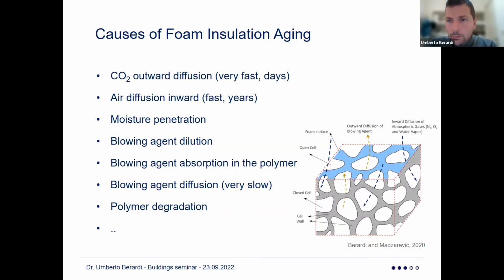And when you get moisture penetration, the thermal conductivity is not anymore the nominal thermal conductivity, but it starts affecting the polymer structure. And really, this is what we often call aging of the foam. The reality is that the polymer starts to degrade, and it occurs a lot in the first month, but it will keep happening for the following years since the installation.